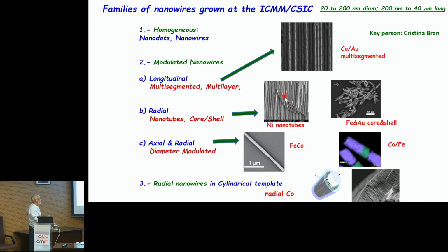This is an array of nickel nanotubes, and these are isolated iron gold core shell wires. But this modulation can also be in the diameter. For example, you see an individual nanowire with alternated segments with different diameter, thin and thick diameter. Also, we prepare radial or cylindrical nanowires in a radial configuration.